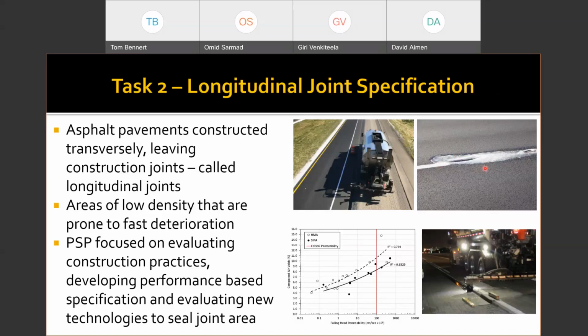So we're looking at ways of improving longitudinal joints with performance specifications, a specification that we developed for New Jersey, which is really based on the permeability that we expect out of those areas, and also looking at ways to seal those joints up. We're running a couple of pilot projects now on a material and a process, if you look on the bottom right here, called a void reducing asphalt membrane, or VRAM for short. And this helps to actually seal up that joint area, not just along the face of the joint, but as you put the hot material above it, it actually wicks up and starts to clog that joint area to reduce water going in. So we're looking at a number of these technologies to help improve that.